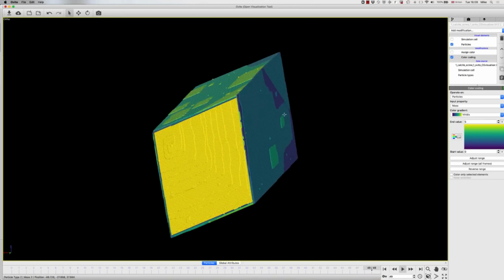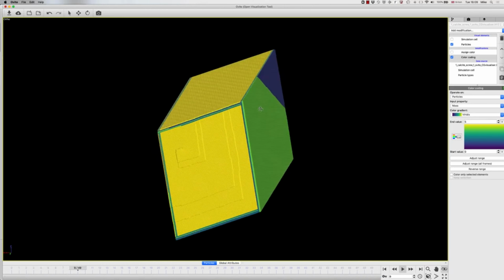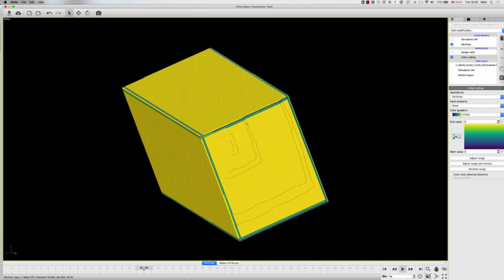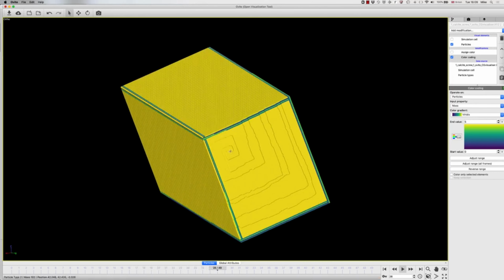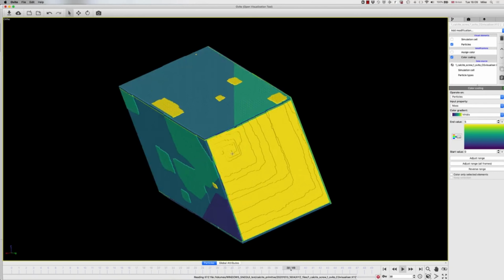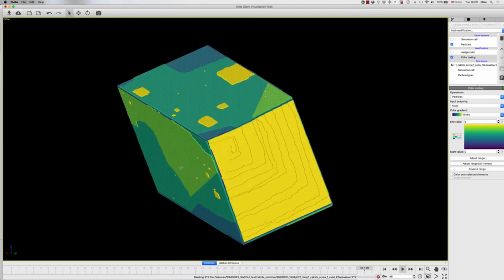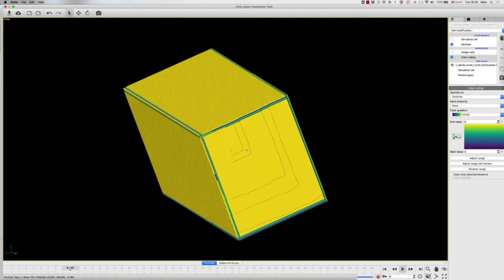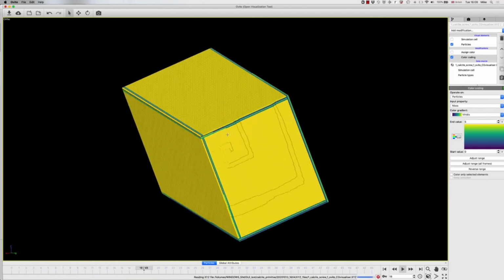So although the colouring is not perfect, we can still see the effect of at low supersaturation only having the growth of the screw core, and then switching on the layer by layer growth at the higher supersaturation.